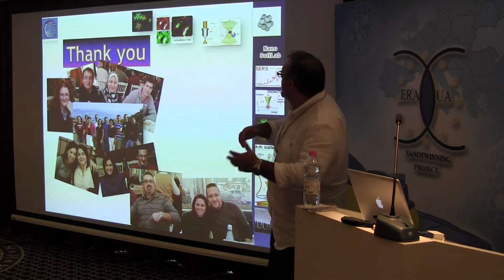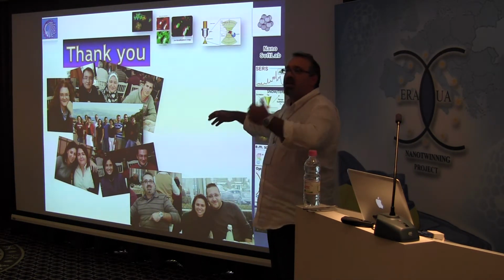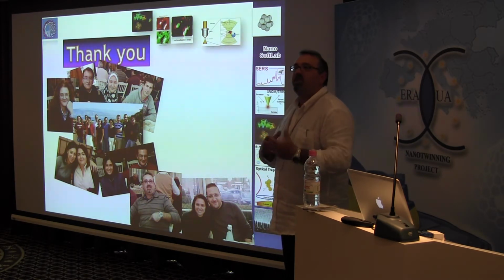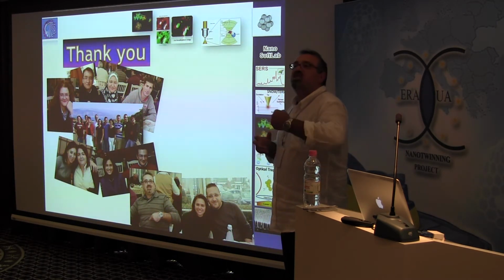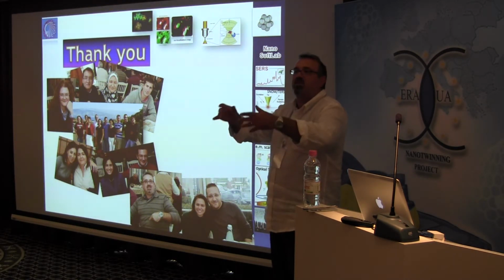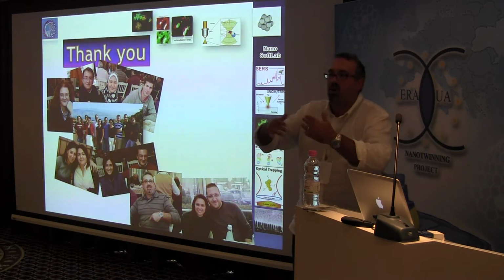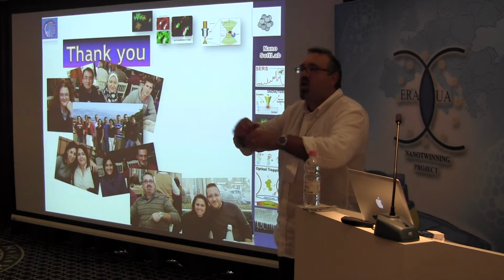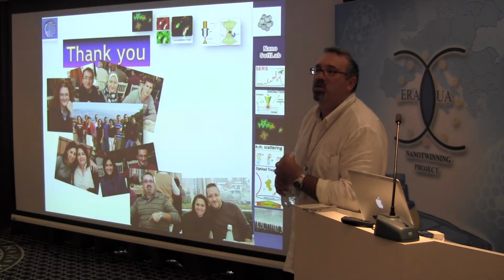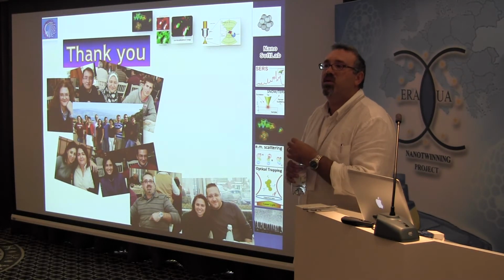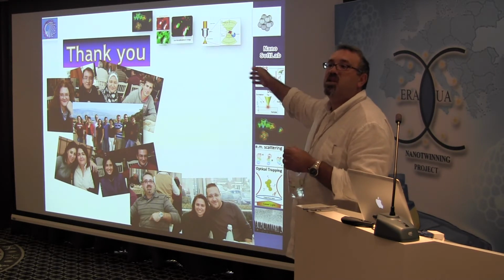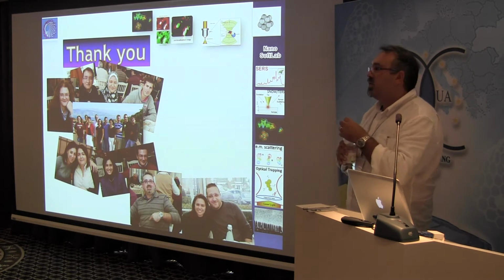Actually, I can tell you something. We are struggling a lot with using these nano antennas and so on. But from the experimental point of view, the most signal you get is when you have rough stuff, whose resonance perhaps is not well matched or not well established, but rough gold gives one or two orders of magnitude more signal than nanoantennas. But okay, if you engineer the localized plasmon resonance, you can do these strange SERS experiments.